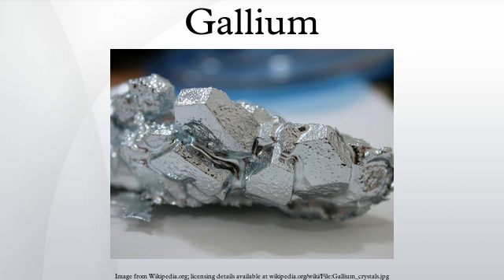Pnictogen compounds. Gallium reacts with ammonia at 1050 °C to form gallium nitride, GaN. Gallium also forms binary compounds with phosphorus, arsenic, and antimony: gallium phosphide, gallium arsenide, and gallium antimonide. These compounds have the same structure as ZnS, and have important semiconducting properties.